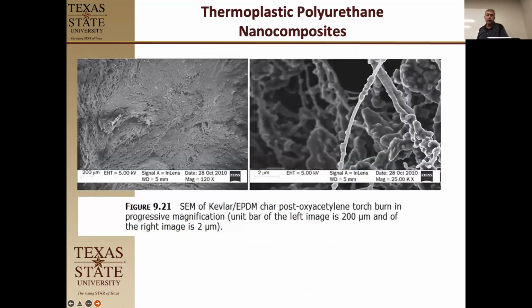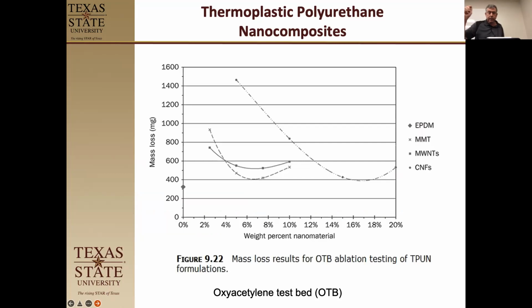Okay. So they looked at the surface of the Kevlar after the torch burn. What they see is some melting of fibers. This is large masses of fiber. Notice everything else is burnt out. You're left with mostly carbonized material binding your Kevlar fibers together. Your Kevlar fibers are pyrolyzed to some extent as well. And so you see these pyrolyzed materials.